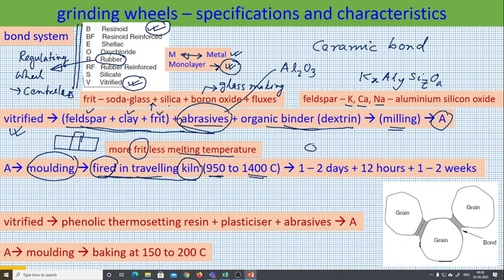Typically, even for a 200 millimeter grinding wheel, not only one would be fired. Possibly 1000 would be fired in a single batch. It would take 1 to 2 days to reach the temperature. Say the temperature you have specified is 1250 degrees centigrade. Then you have to hold it for homogenization of the temperature. And the cooling period can be as long as 1 to 2 weeks for larger wheels, not for 200 millimeter wheels, but say 450 millimeter wheels which are used in cylindrical grinding operation. They can be 1 to 2 weeks. Because this being a ceramic bond, if you cool it very fast, there would be bond fracture.